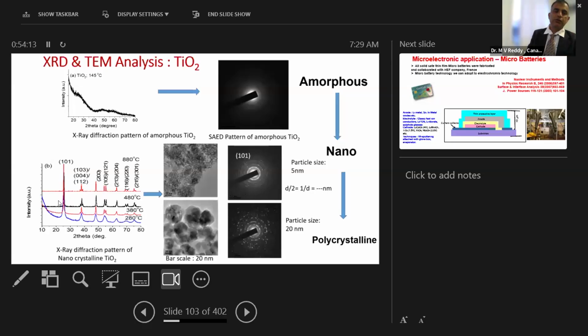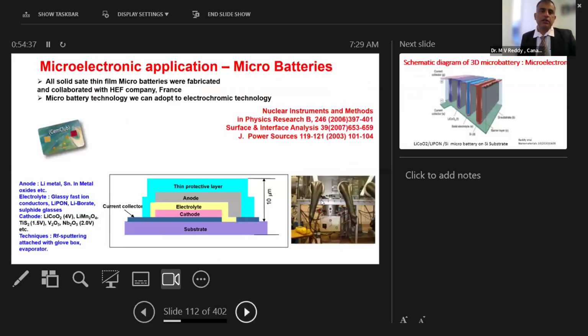Typically, we get the d-spacing from these values: the inner ring corresponds to the diameter divided by 2, then 1 over that gives the d value, close to what we get from XRD. That is why TEM people and X-ray people can complement each other in the analysis of the material. Especially for thin films, if you want to do layer by layer growth, we need something like cathode, anode, electrolyte, and separator. A glove box is needed, since it is a lithium-containing sample and air sensitive. So we have to work together.